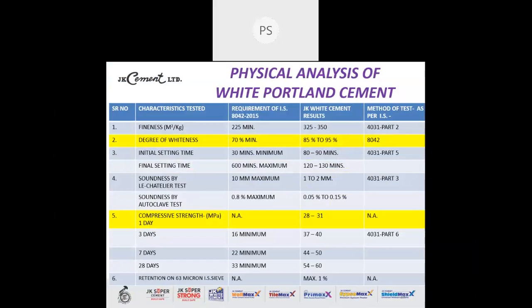Now we look at point number 1, that is the fineness. It is measured in meter square per kg. IS code says it should be minimum 225. We get a range of 325 to 350 meter square per kg for JK White cement. If you see, it is finer than any other OPC cement. Now, initial and final setting time, again the same, 30 minutes minimum, 600 minutes maximum. We get a setting time IST of 80 to 90 minutes and FST between 120 to 130 minutes. Now, soundness test, again the same, Le Chatelier 10 mm.